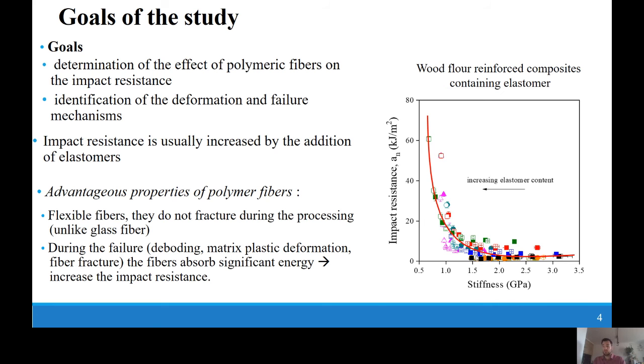The aim of this study was to determine the effect of polymeric fibers on the impact resistance of three-component hybrid PP materials and to identify the deformation and failure mechanisms occurring during deformation. Impact resistance is usually increased by the addition of elastomers. However, this method of modification decreases the stiffness of the material to below 1 gigapascal at large elastomer content, which is not accepted in many applications.